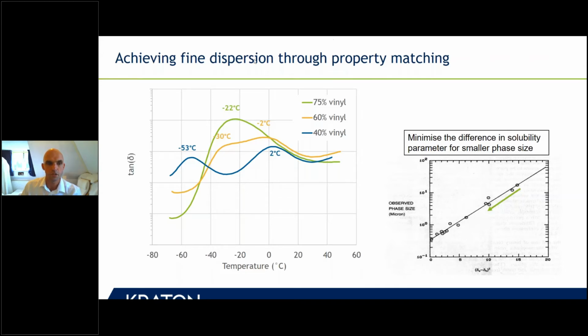By increasing the vinyl percentage, or actually to be chemically correct, the butylene percentage, you bring together the rubber Tg, which is on the lower side, and the amorphous phase Tg of the mid block, and you bring them together to 1 Tg, which actually matches the Tg of polypropylene fairly well. So that's one reason for compatibility. Moreover, there's also chemical compatibility, and this was mentioned before as well. The matching in solubility parameter. The better the match in solubility parameter, the smaller the phase size.